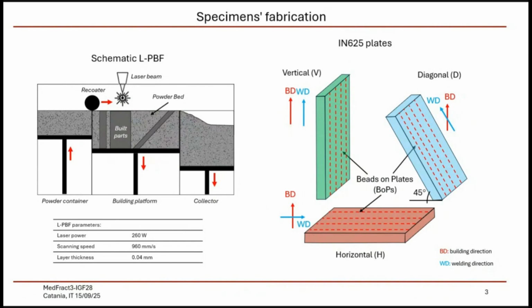And the 3 plates that we use were printed in 3 different building orientations: vertical, horizontal, and diagonal, with a 45 degrees inclination, which is the threshold to avoid support materials. On each of these plates, 4 different BOPs, bead on plates, were welded using laser beam welding.